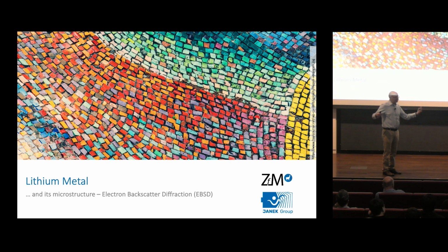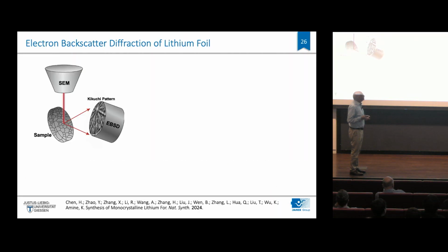In principle, you have to cut and look at it with a suitable technique, and that was, before they did their work, not possible. So essentially what they used was a technique called electron backscatter diffraction. Essentially, it's a technique where you use an electron microscope. You have an electron beam.